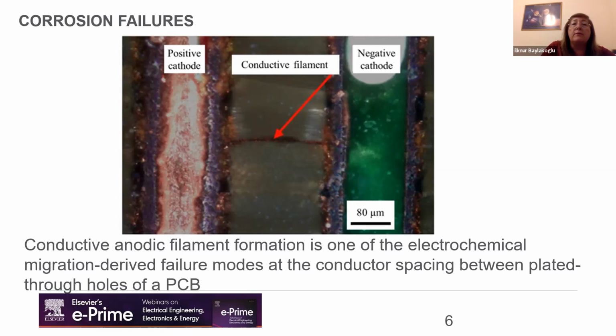It is really difficult to predict this copper filament, and the effect of some microorganisms also can cause this type of result in humid environment. So some very weak acids are produced during the metabolism of these microorganisms, and they can cause the corrosion. Because of this, in some of the high technology and high reliability projects, they ask for the fungus resistance test, which is able to show the effect of the microorganisms.